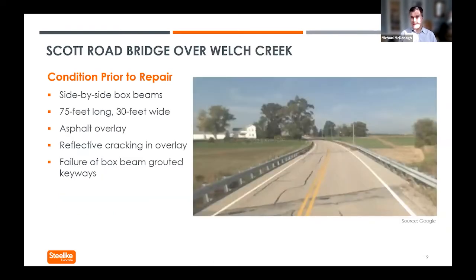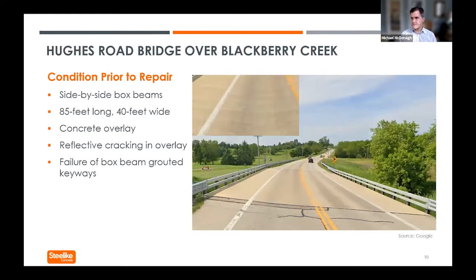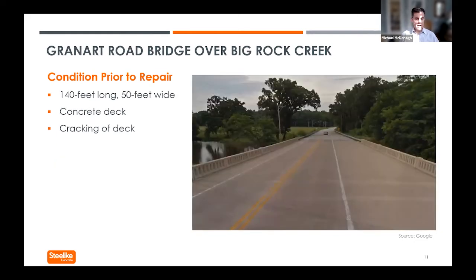So the Scott Road Bridge, shown in this photo, is one of the side-by-side box beams, about 75 feet long, 30 feet wide. And you can see in the left lane in the photo some reflective cracking coming up through the asphalt overlay, indicating that the box beam grouted keyways had failed. The Hughes Road Bridge is a similar bridge, similar condition, except it has a concrete, or had a concrete overlay. And in the little zoom in photo in the top corner, you can see some of that reflective cracking appearing in the overlay. So once again, grouted keyways were failing, which was leading to advanced deterioration of the box beams below.